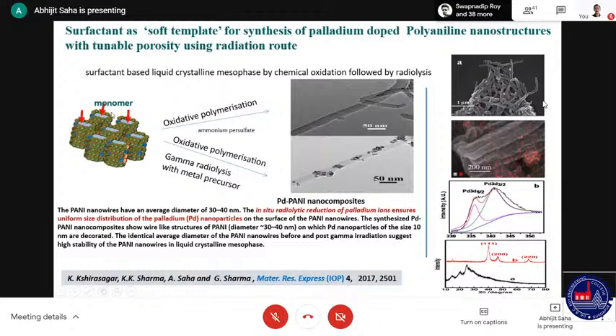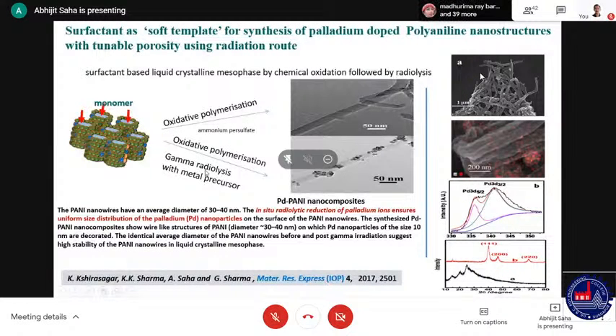Here you are taking the monomer, and we allow it in the radiation field to grow in the form of polymer. So oxidative polymerization is taking place, gamma-catalyzed, with a metal precursor. Then we are getting this kind of structure. So both polymerization and metal are inside. Metal particles are also formed. Both processes are going on in the same radiation field. So this is a very, very interesting observation and work.